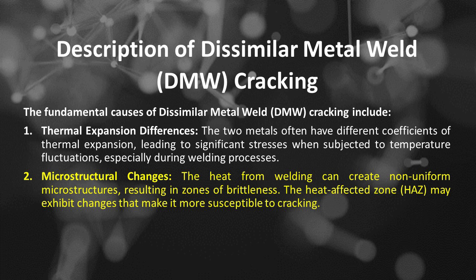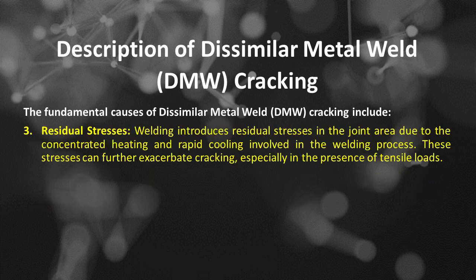Number 2 is microstructural changes. The heat from welding can create non-uniform microstructures, resulting in zones of brittleness. The heat-affected zone, or HAZ, may exhibit changes that make it more susceptible to cracking. Number 3 is residual stresses. Welding introduces residual stresses in the joint area due to the concentrated heating and rapid cooling involved in the welding process. These stresses can further exacerbate cracking, especially in the presence of tensile loads.